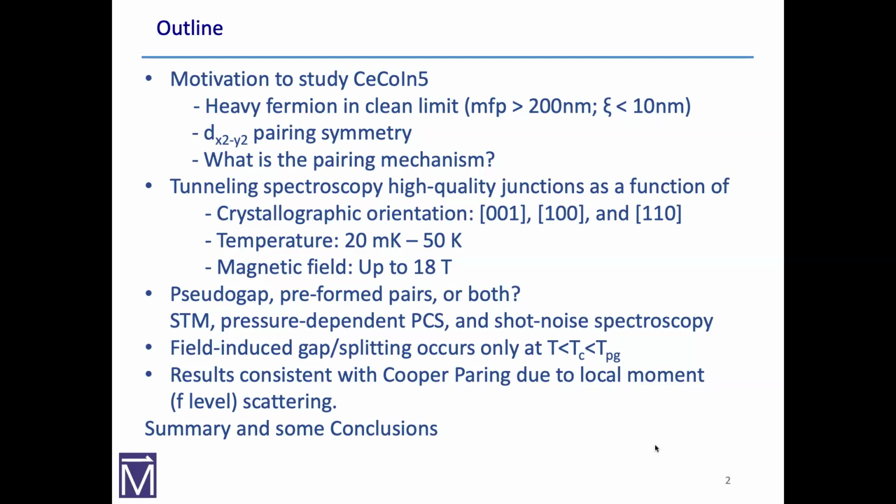So in the cuprates, for many, many years, we've known the pseudogap in the cuprates is pretty complex. And there are places, like what Ong had done a while ago using the Nernst effect, where certain areas in the pseudogap seem to be exhibiting preformed pairs. And in several materials, like some of the iron-based superconductors, there's a lot of evidence for preformed pairs. And I don't think that's a weird idea anymore. I did when I was younger.